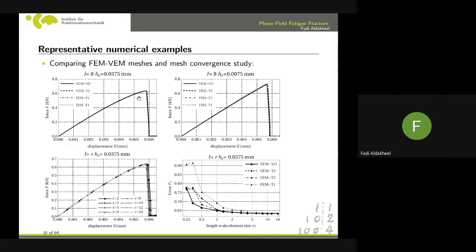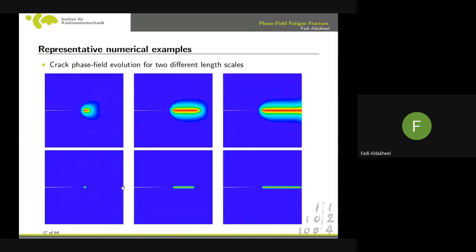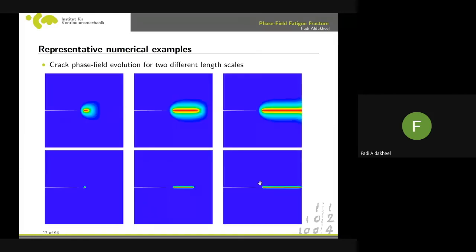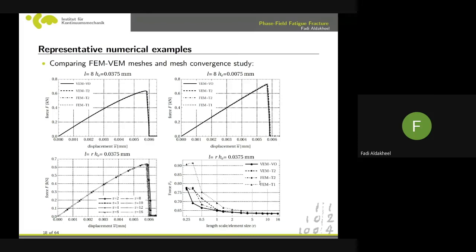And we talk about this fracture length scale L, right? It is linked to the element size or the mesh size, because at some point you discretize the body, and at some point you have the element size, and from that we need to deduce the length scale. So there are two ways: either you have it as a geometric parameter taken from the mesh, and you link the length scale to the element size, or you can have it physically from the GC criteria.